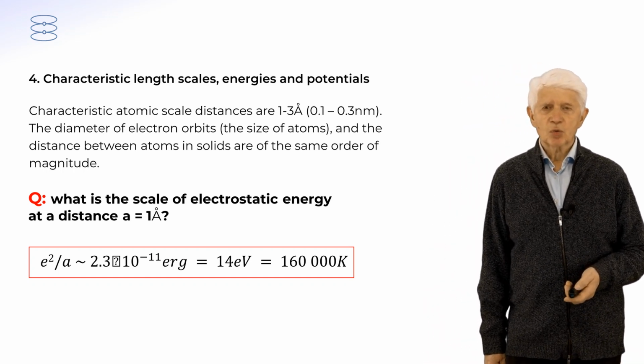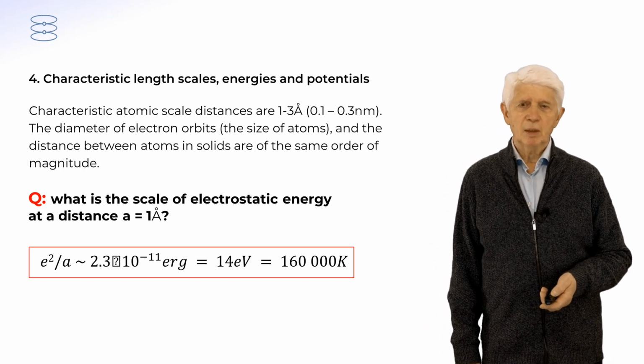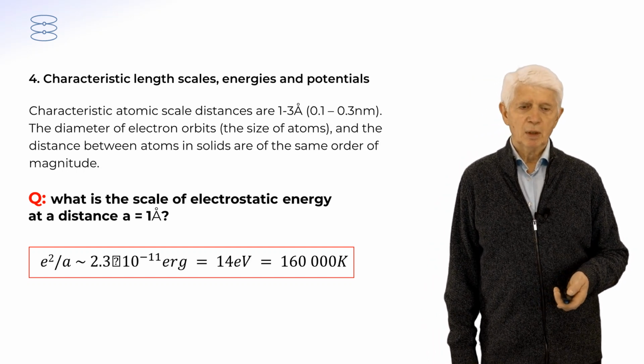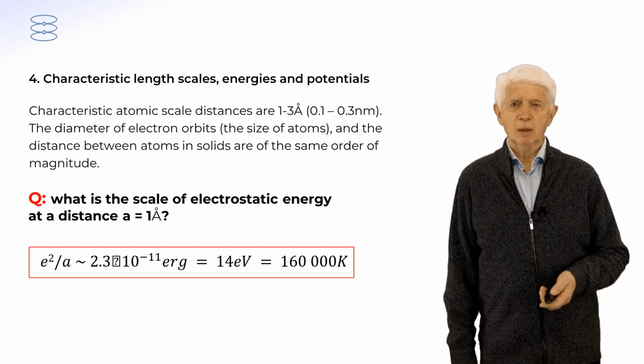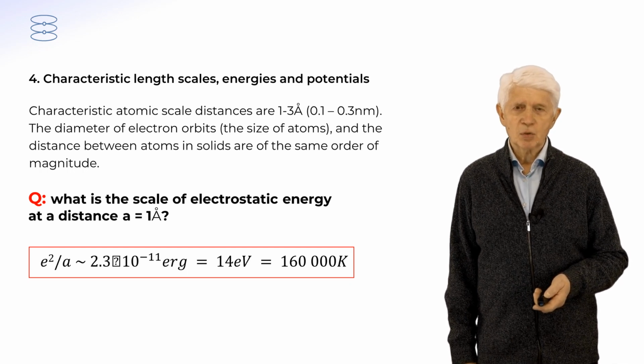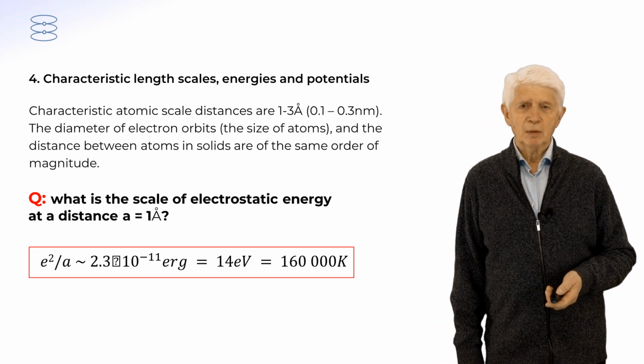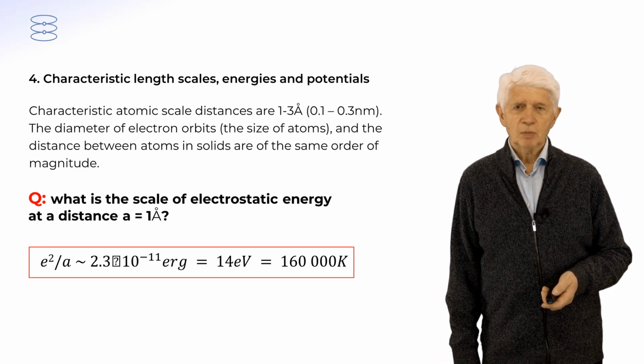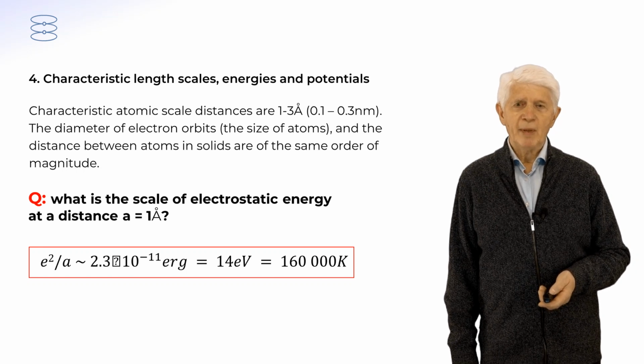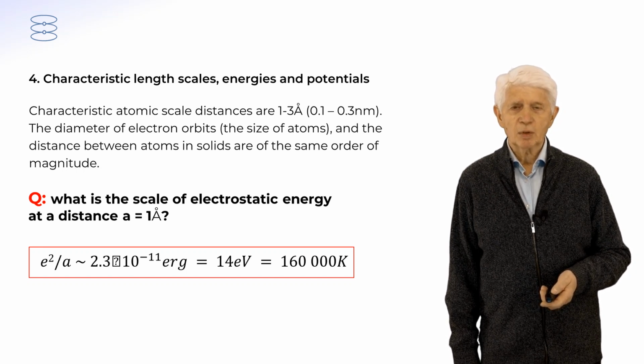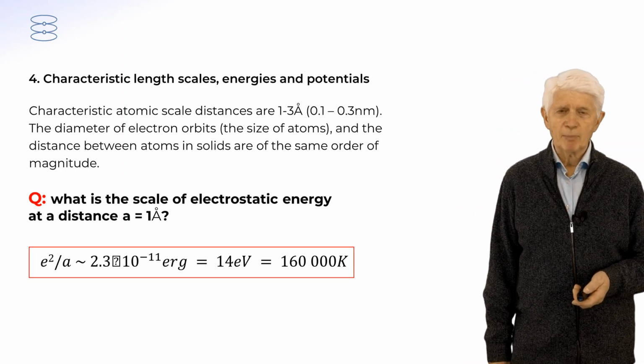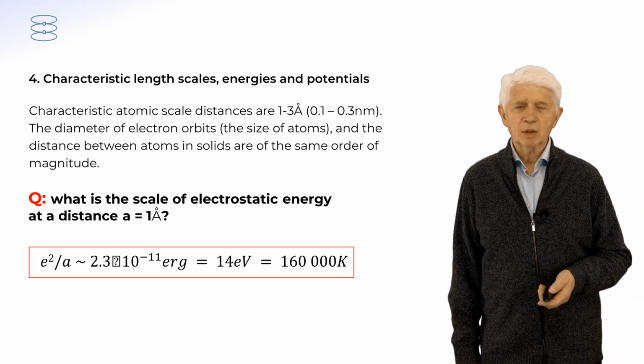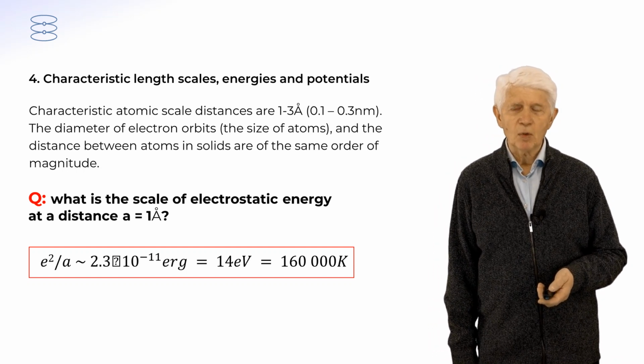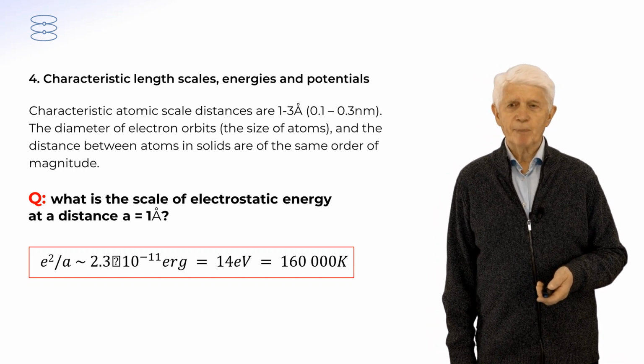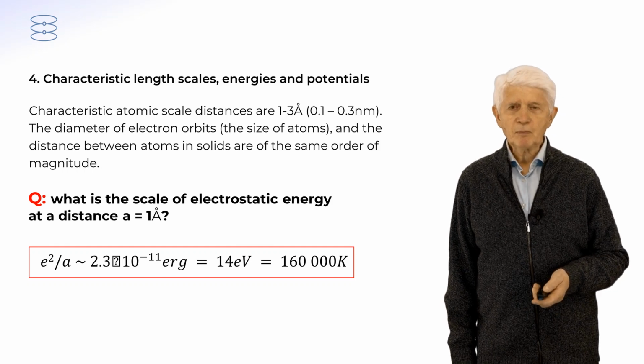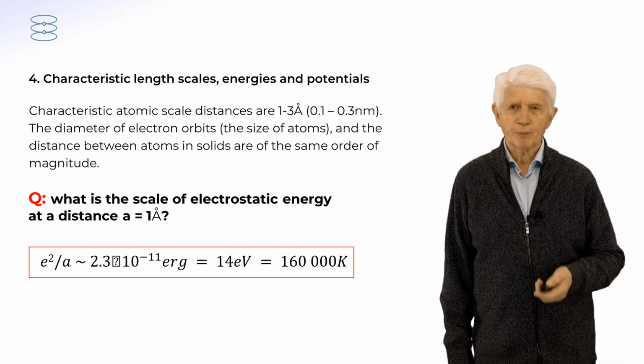At this point, you should think that if you take, say, differently charged atoms like sodium chloride, salt, which is used every day, their atoms are differently charged. It should, according to our estimation, melt at about this temperature, which is not, in fact, what happens in practice. The melting temperature of salt is much lower. And this is because the Coulomb attraction energy is not the only parameter in the problem.